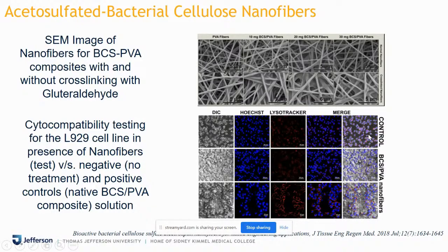And we can see over here on the bottom panel, you have the control, the untreated sample. Then you have the bacterial cellulose sulfate PVA solution only, and the nanofibers that were created. You can see over here the blue and red staining which stains the DNA as well as the organelles of the healthy cells. You can see that the nanofibers not only help to grow the L929 cells, but also help them to stick on the surface, and the morphology was also healthy. So this was a unique development that we did in terms of nanofibers, where we can show the use of these nanofibers for potential regenerative medicine applications.